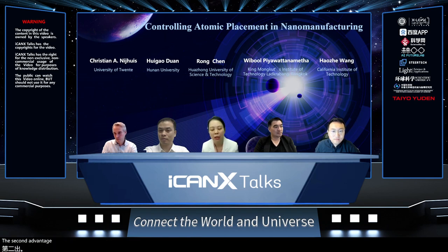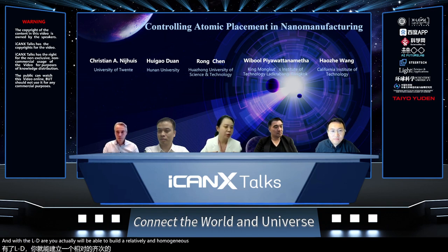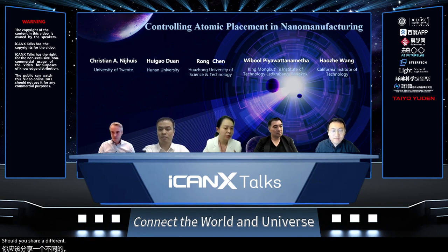The second advantage is that many of these studies involve structure-activity relationships. With ALD, you will be able to build relatively homogeneous structures very well. That helps you build up structure-property relations better than when you synthesize randomly and then have different size distributions and different structures. Fundamentally, it helps you understand the properties, which is very good. But definitely, at least at this moment, it's much more expensive than wet synthesis, so we have to rely on real applications to reduce the cost.